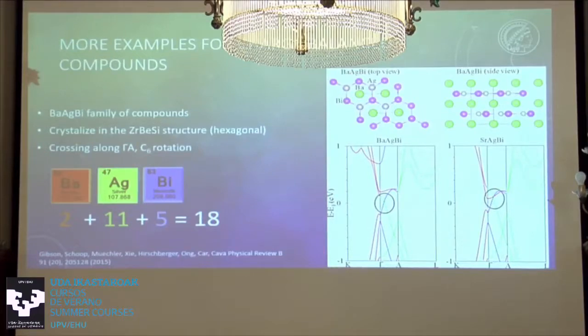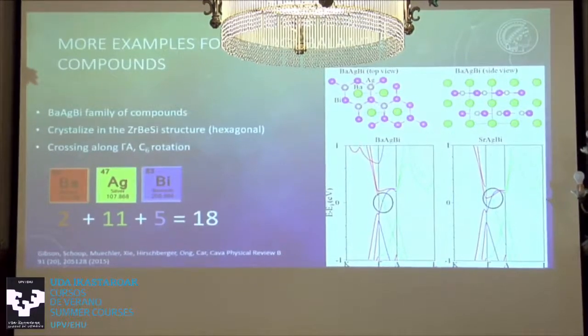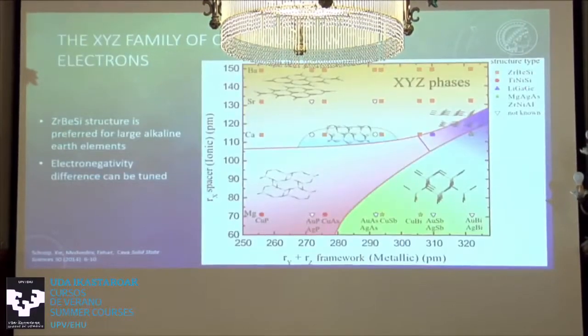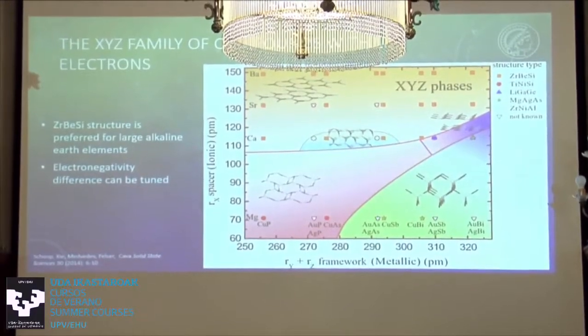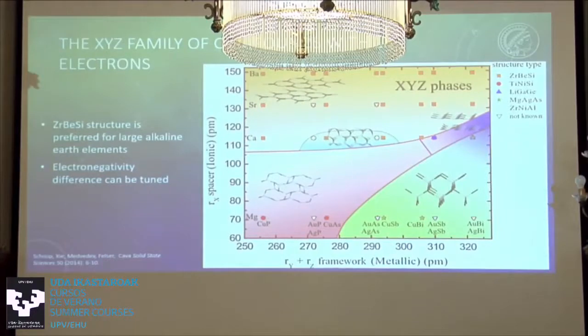But strontium, silver, bismuth already has the crossing up here and some mixing through it. So basically, this brings us back to the structural map we had before. All those orange phases are the phases where a 3D Dirac semimetal is possible, and those are all the compounds. And so we tune the electronegativity difference in the phase along this arrow here. So we have some degree of tunability.